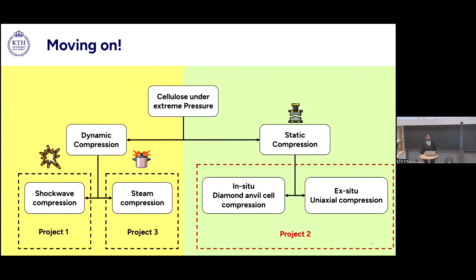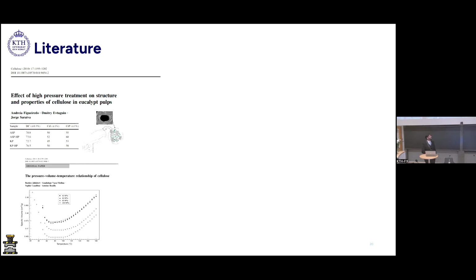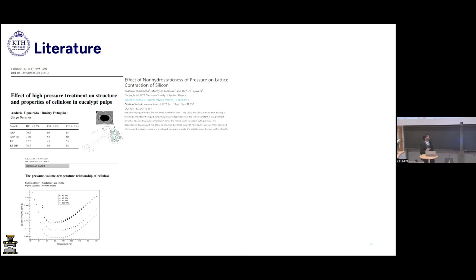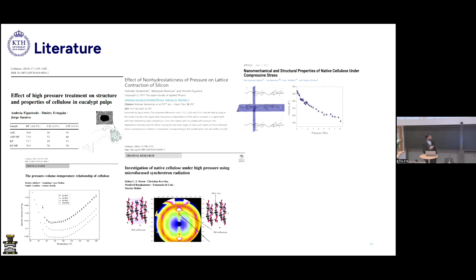Moving on. We will talk a little bit about static compression experiments, where we wanted to establish a little bit of literature review, and here we were a little lucky because there was some research done in this area. One research from Portugal compressed the cellulose pulp at roughly 400 megapascals of pressure and reported a slightly higher crystallinity. Another research did the bulk compression of cellulose and established a non-linear relationship between cellulose volume versus temperature and pressure. Also, another research suggested that as long as you have a pressure transfer media in liquid form, it will have a certain trend in the lattice volume contraction, and when it changes to solid due to the extreme pressure values, the trend in the lattice volume contraction will change.